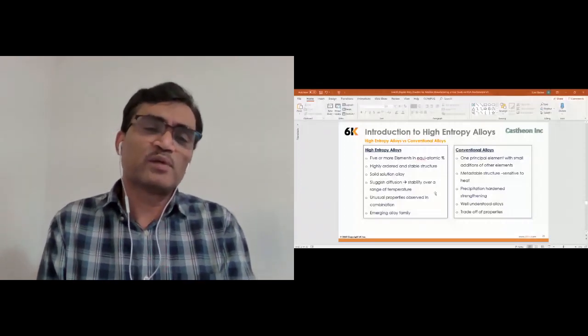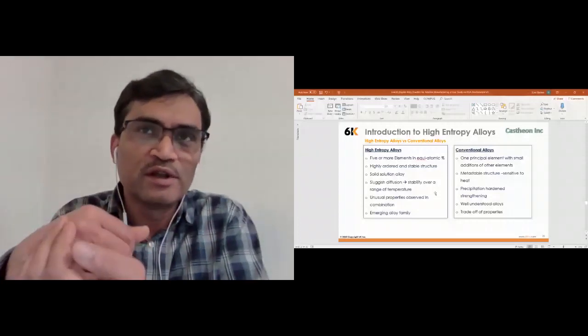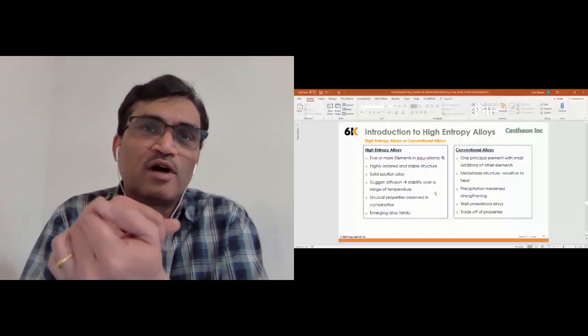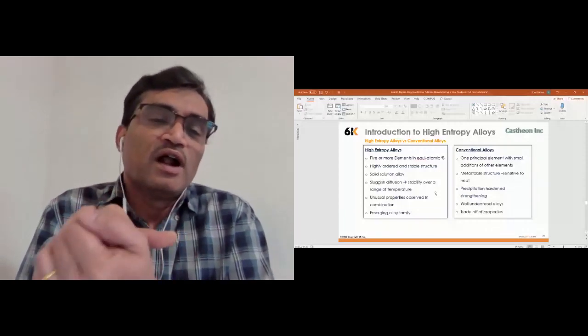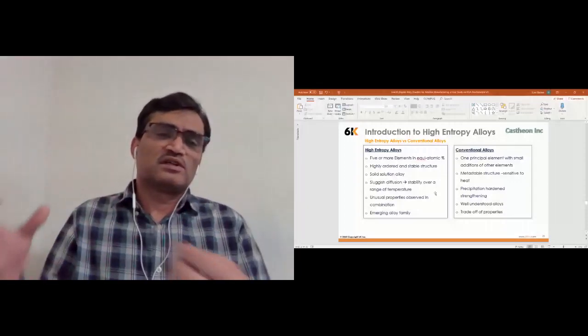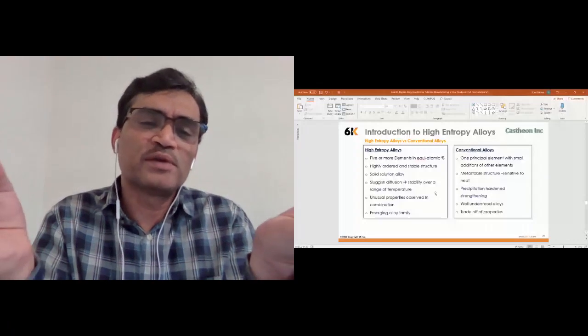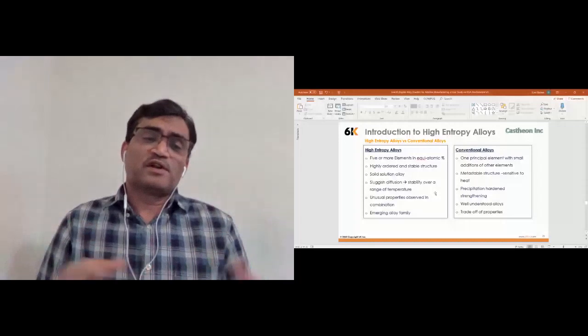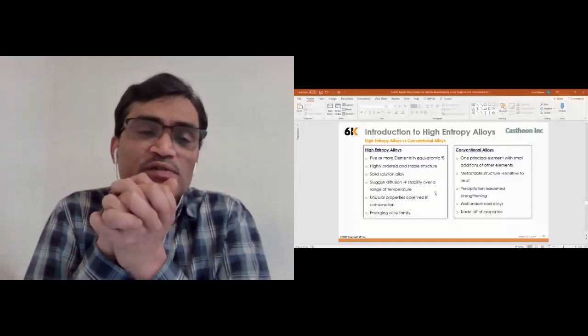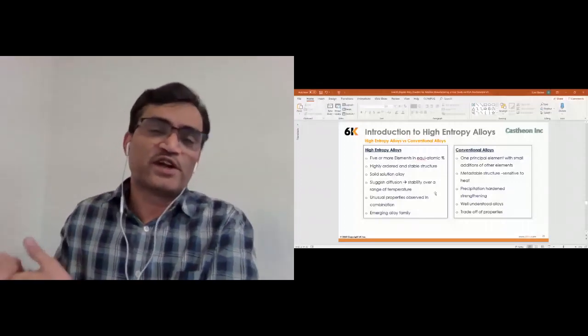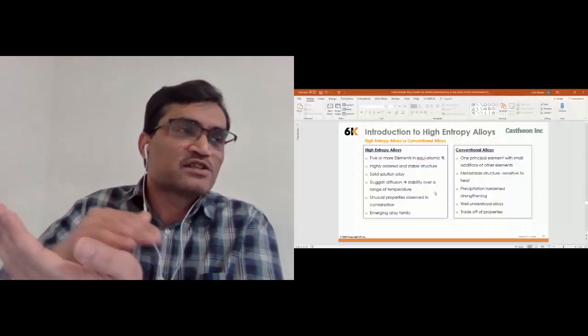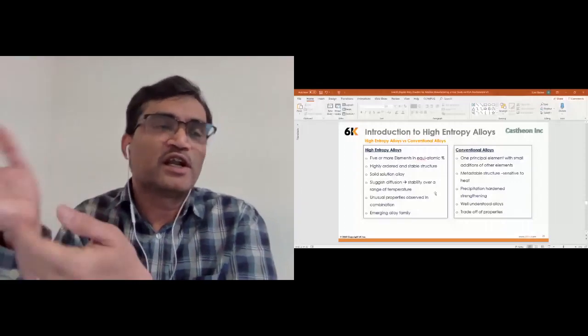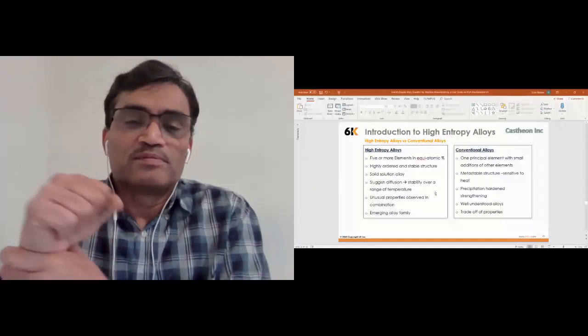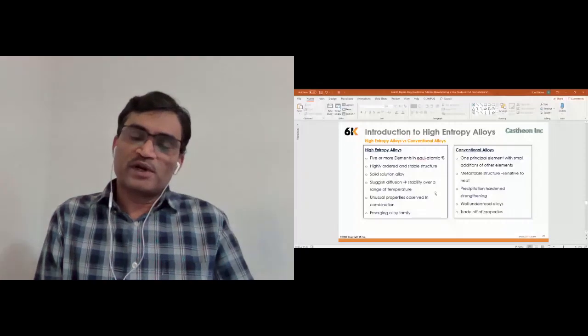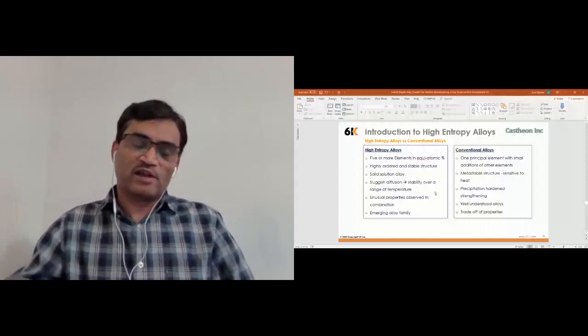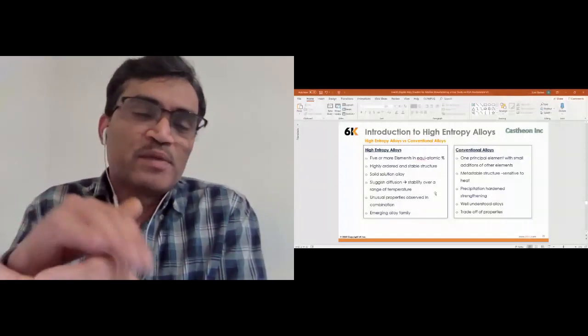The other advantage of high entropy alloys is sluggish diffusion, and that's mostly because it's a single phase alloy. Most of the time, it's a solid solution alloy with an equiatomic composition of 5 or more elements. So diffusion becomes very sluggish over the temperature range, and that can be an advantage, in that the properties can be stable over the temperature range. Generally, in conventional alloys, the room temperature properties and high temperature properties are vastly different, and that becomes a stability issue over the temperature range.